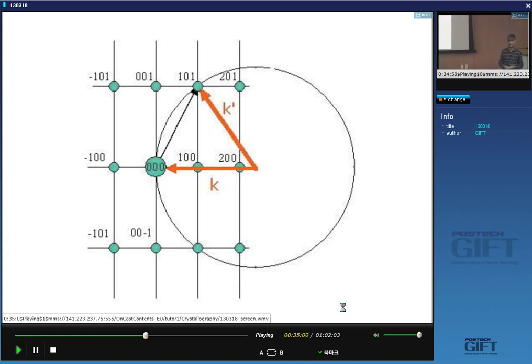So the Ewald sphere construction helps you to identify which planes are going to give you diffraction. And here we are using a monochromatic wavelength. Now supposing you are using white X-rays, that means a range of wavelengths. Then say this is the minimum wavelength here, 1 upon that. And then if I have a smaller wavelength, I would have a larger sphere here. And anything falling between the minimum and maximum radii would contribute to diffraction.